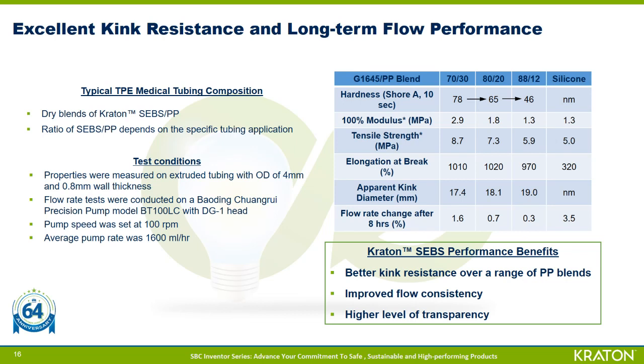In this table, we have shown a comparison of the tubing properties made with G1645 and polypropylene blends at 3 different ratios, and also performed the same tests on a silicone tubing. It can be seen from the decreasing Shore A hardness here that the G1645 polypropylene tubes become softer with increase in G1645 SEBS. So you can really tailor the hardness by varying the proportions. Tensile strength decreases slightly, while ultimate elongation is well above 900% for all the G1645 polypropylene compositions. And what we can also see is that the modulus of these tubes is quite similar to that of silicone